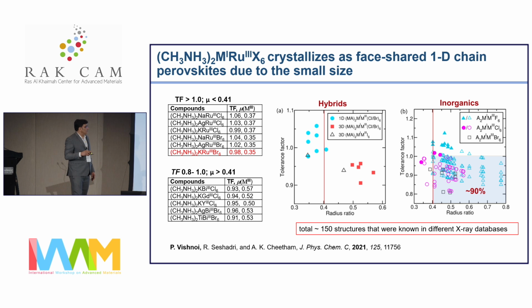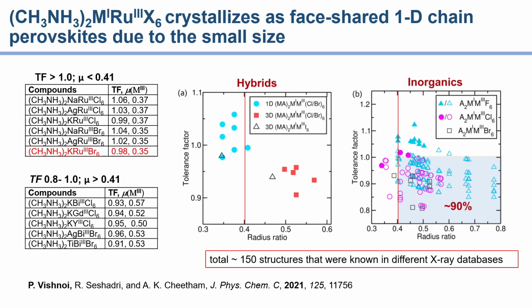the known inorganic compounds. At that time, about 3 years ago, close to 140 all-inorganic compounds were known, where the A cation is cesium instead of methylammonium. And what we see is our model, which we designed based on these two parameters, actually predicts most of these structures, and that accuracy is close to 90%. That means the message here is that using this combination of tolerance factor and radius ratio, one can even predict a compound which is not discovered before and say whether it's going to be 1D or going to be 3D.